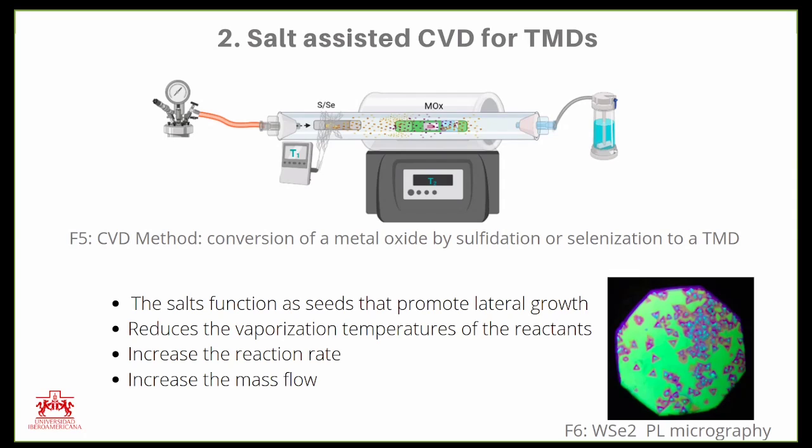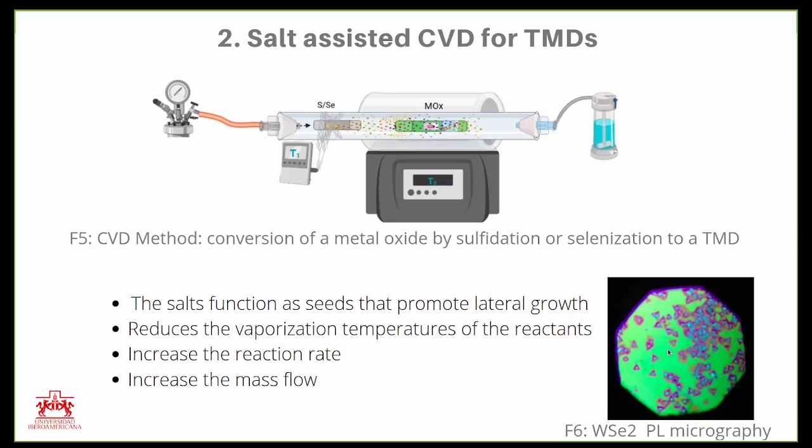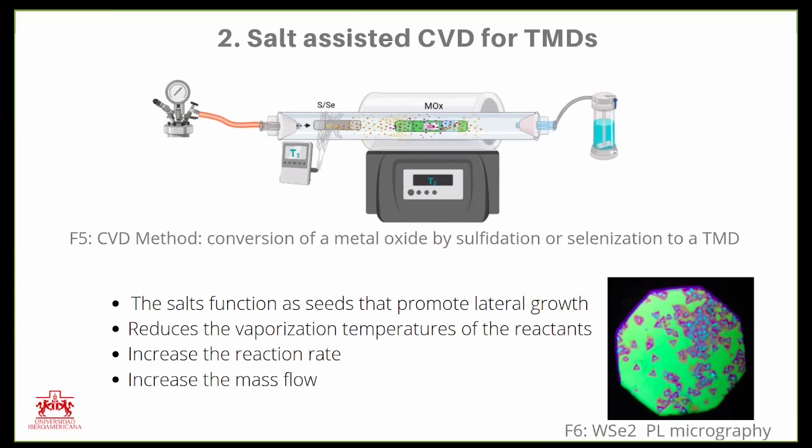But if we are not careful enough or let it go a lot of time, we will have oxides, and the sample will be contaminated. Yes, these white spots, those are oxides, but with the temperature, they disappear later.